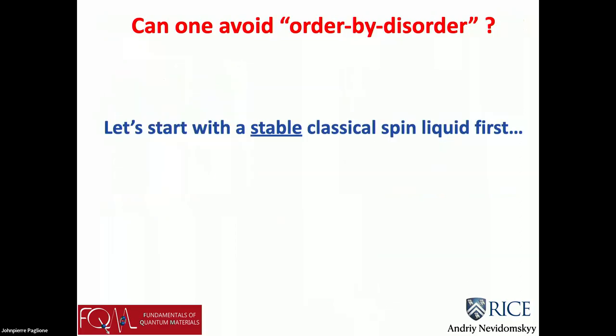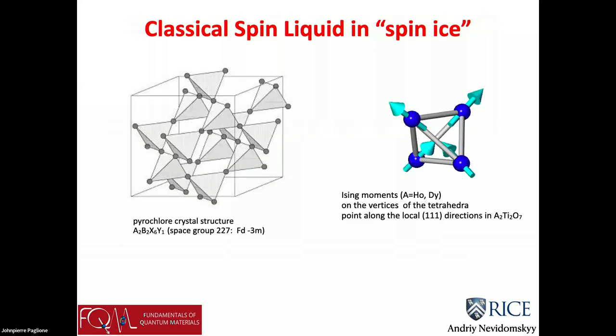All right, now, can one avoid order by disorder? Well, first, remember the only example I gave you of a classical spin liquid was the Vannimenus calculation on a triangular lattice, but those were Ising spins, right? So let me give you one example, which is well established in the literature. That's what people refer to as classical spin ice. This is an example of compounds on the pyrochlore lattice. And okay, so Ho2Ti2O7, GT can tell you probably more than I can about this.